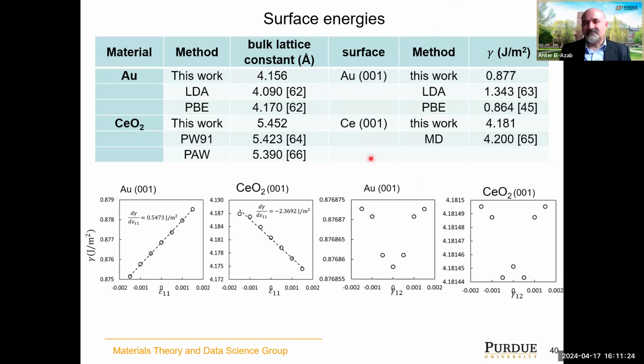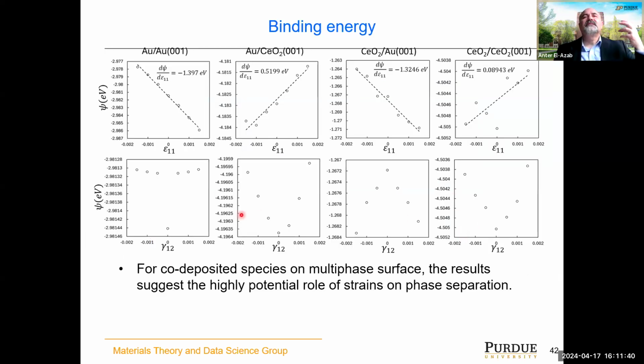the surface energies as well. So that's the surface energy as a function of strain. It shows that it does vary. It is more sensitive to the tensile and compressive strain than the shear strain. And he computed the dependence of the energies, the hopping energies and the bonding energies on the strain. He spans a strain from negative to positive values, that's compressive to tensile, and also shear being from negative to positive values. The uniaxial or the normal strain components are more effective in changing the bonding energies than the shear components.